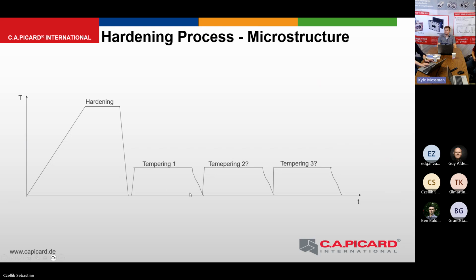We have different materials with different tempering steps. So the tempering depends on the one hand on the alloying contents and what we want to reach. If we have a material with a lot of retained austenite, we normally have to do 3 tempering steps, but we have some materials where we don't need that. There we do 1 or 2 tempering steps. It really depends on the material. And we have different tempering temperatures depending on the material. We often use secondary hardeners where we build carbides by the tempering.